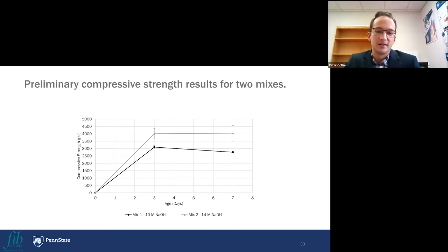The 10 molar sodium hydroxide solution has a compressive strength around 3000 PSI, kind of bouncing around there at the 3 and 7 day mark, whereas the 14 molar sodium hydroxide with the higher pH resulted in strengths of around 4,000 PSI. It's important to note a lot of these geopolymer concretes don't continually gain strength after the initial curing period that's been reported before. It's not always the case, but it's different than Portland cement, where you're getting continual strength gain throughout the first 28 days where it starts to taper off. So these are just kind of bouncing around their initial strength gain at the 3-day and 7-day marks.